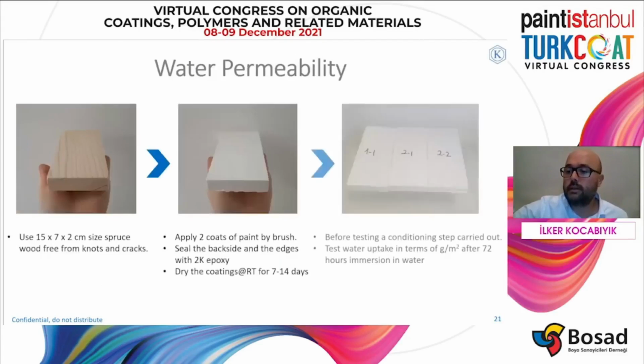Water permeability test is carried out according to the EN 927-5 norm. The paint is applied in 2 layers by brush on spruce wood panels. The backside and edges are sealed with 2K epoxy, and after some preconditioning steps, panels are floated in water, painted faces down, for 72 hours. After 72 hours, the water uptake in grams per square meter is calculated for each test panel.